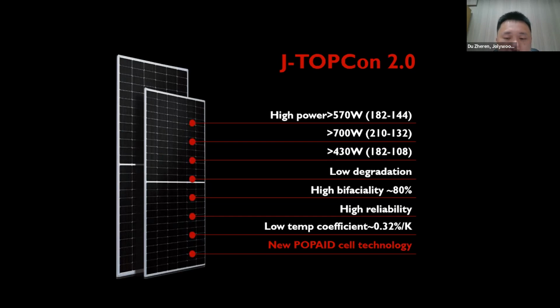And also our product has very low degradation, high bifaciality, high reliability, and low temperature coefficients. These properties contribute to an increased electricity generation during the module life cycle. And according to our calculations, 30 watt module power increase will lead to around 1.5% LCOE drop. 10% higher bifaciality will lead to about 1% drop in LCOE. And the lower temperature coefficient will lead to about 1% drop. And also the lower degradation will also lead to 2 to 3% LCOE drop. So in total, we expect 5 to 10% LCOE drop.